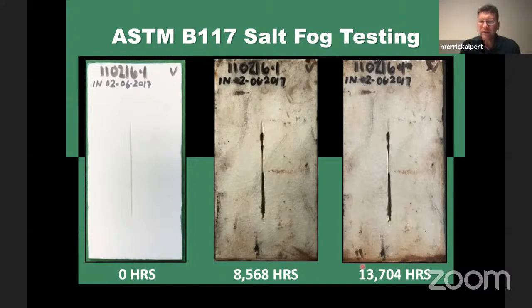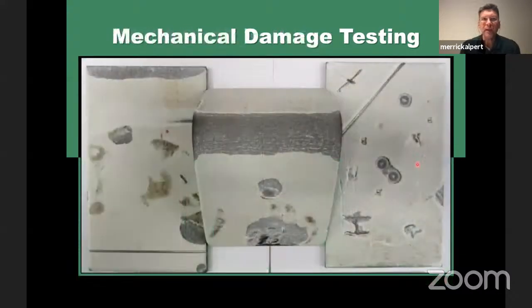Now look at this slide. It's like a time-lapse film that you're watching move along. Here at 13,704 hours, it's about 1.5 years, about 18 months. Same thing, no growth of the scribe line because, of course, you've passivated the steel beneath it. We actually used a little light grit sandpaper here to demonstrate that this area out here was just stain, not rust. And so we scraped that away so you can see it.